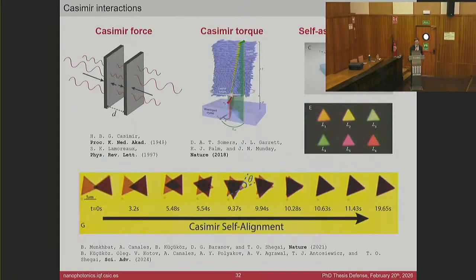Yes, there's indeed a peculiarity, which is that these nanostructures are inside a fluid, and in particular an ionic fluid. And when I say that by tuning the properties of the environment, you could tune the equilibrium distances between these flakes and its resonances, it's because you can also play with the properties of the fluid and add higher or lower concentration of ions. And these ions are playing the important role of giving some kind of electrostatic repulsion that is compensating with this attractive Casimir force.